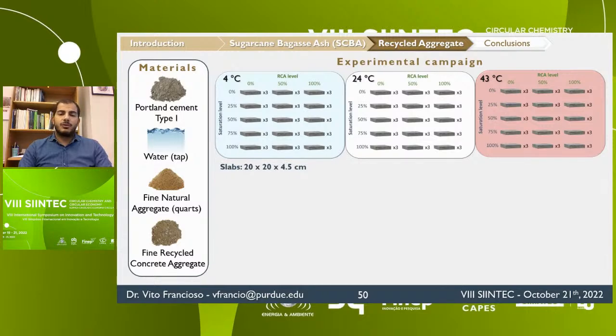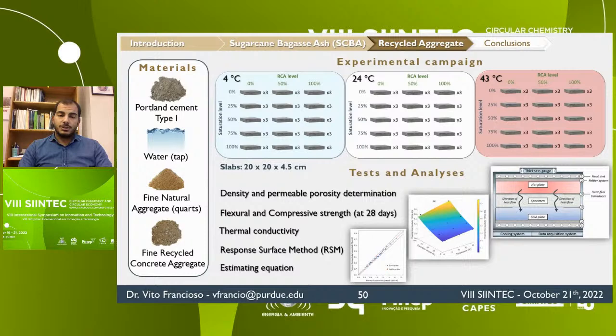So prismatic specimens were cast for flexural strength and compressive strength tests, and slab specimens were cast for thermal conductivity evaluation. A total of 135 thermal conductivity tests were performed here. Each sample was tested at 3 different ambient temperatures, 4, 24, and 43 degrees Celsius, as per the RILEM standard. And also 5 different saturation degrees were studied, from dry to fully saturated condition. The density and the permeable porosity were also determined, and finally I designed an equation which allows us to obtain the thermal conductivity as a function of different variables that we will see later.